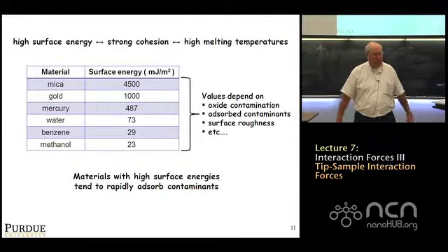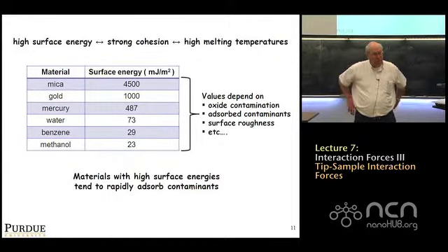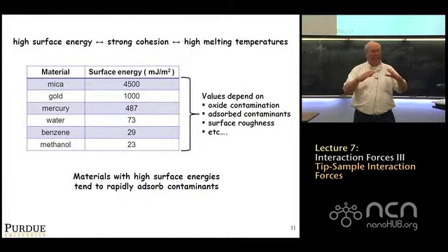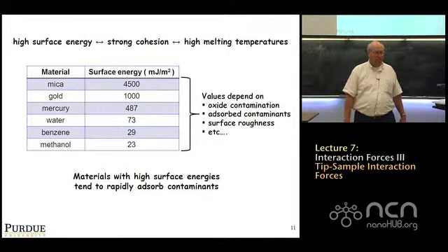There's a question. How is the surface energy of a solid measured? Well, the surface energy of a solid tends to be measured by putting a drop of a liquid with known surface energy onto the solid surface, and then you measure, let's say, the contact angle that the drop makes with respect to the solid surface. There's an equation by Young and Dupre that allows you to work backwards from the contact angle and get the surface energy of the solid.